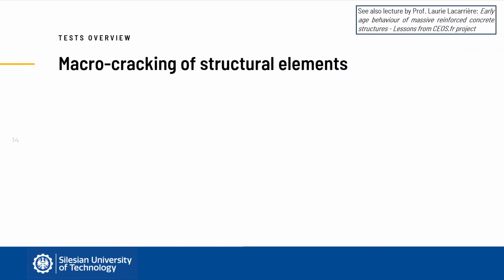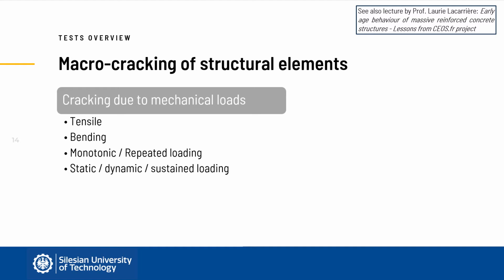There is a wide range of tests which can be performed to characterize cracking in reinforced concrete structures and structural elements. As for the cracking due to the action of mechanical loading, typical tests of concrete under tension or bending are performed, in which the load can be either monotonic or cyclic, and with a different rate of the applied strain. This allows to model the behavior of reinforced concrete elements under various typical as well as accidental loads to which they can be subjected during service life.